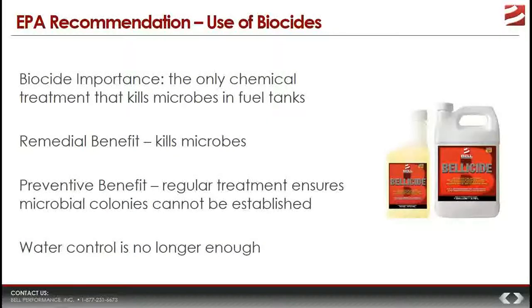If you treat it with a biocide, that's the first essential step to killing those microbes, and it is the only way to stop microbially induced corrosion from progressing. That makes biocide treatment a remedial benefit. On the preventive side, they recommend that you don't just treat one time, but you treat with low levels of biocide on a regular basis, on, let's say, a quarterly basis.